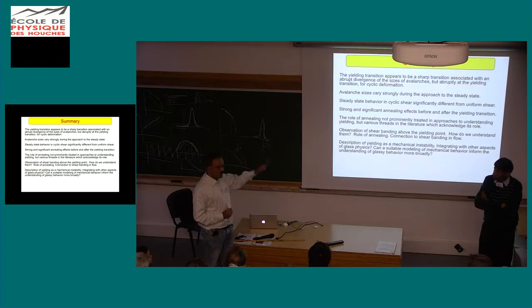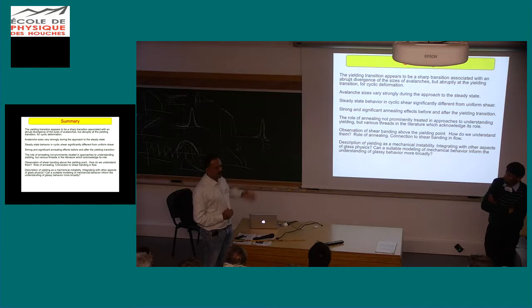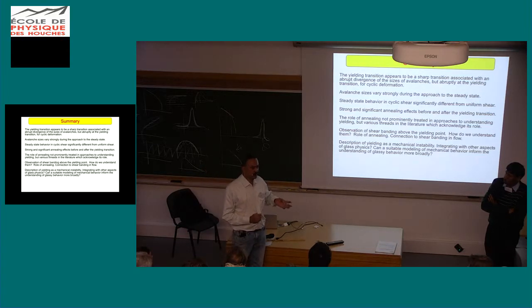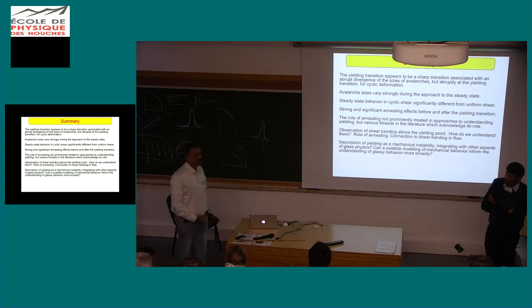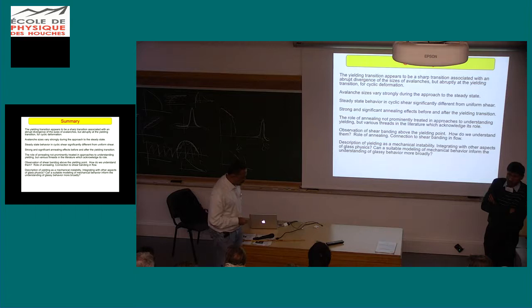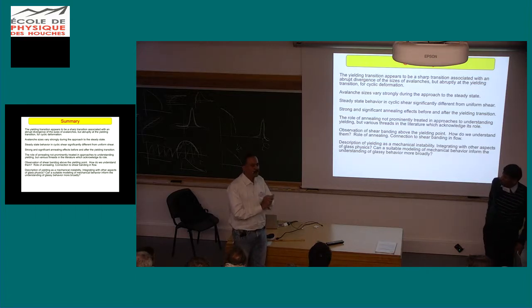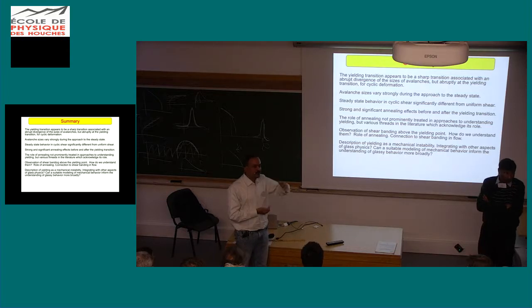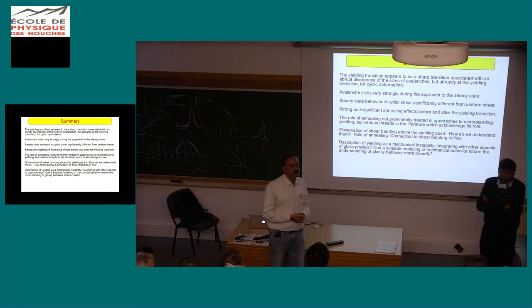So here, in the results that I presented, there are no thermal effects, like I said at the end. Something like shear banding does seem to happen also when you have finite temperature. But basically, this is a hand-waving sort of explanation. If you have in mind a picture that better annealed glasses will have a larger yield strain, as you anneal the glass, there is a limit up to which you can accommodate the strain that you're applying by annealing the glass to lower states. But there is a threshold, a point of mechanical stability for any glass that you may have.